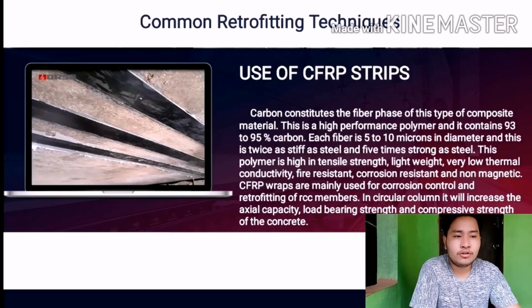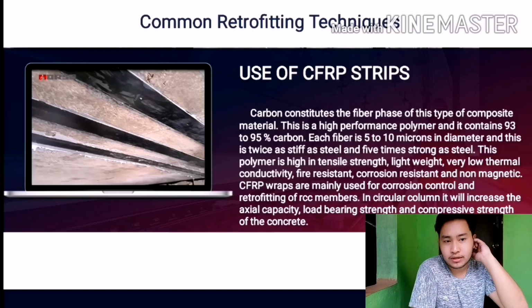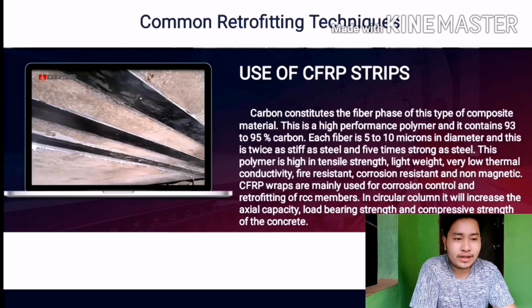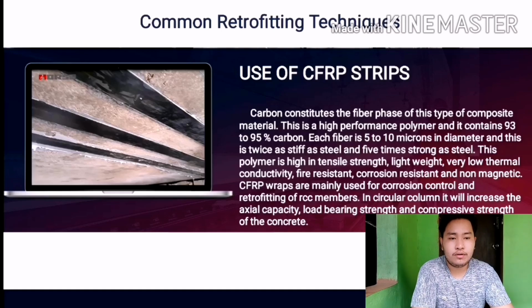Carbon constitutes the fiber phase of this type of composite material. This is a high-performance polymer and it contains 93 to 95% carbon. Each fiber is 5 to 10 microns in diameter and this is twice as stiff as steel and 5 times strong as steel. This polymer is high in tensile strength, lightweight, very low thermal conductivity, fire resistant, corrosion resistant, and non-magnetic. CFRP wraps are mainly used for corrosion control and retrofitting for reinforced concrete member.